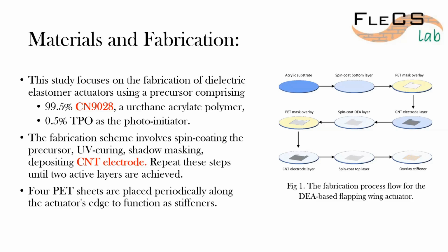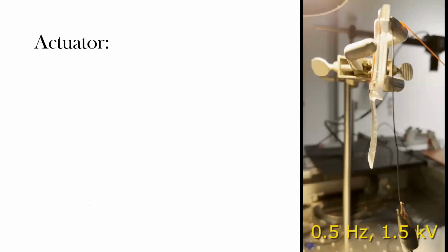And, of course, at the end, if you want a specific kind of actuation, like I said, you have to do some kind of physical constraining. In this case, we did that constraining by overlaying a stiffener, which is a PET thin film, stiffer than the elastomer itself. And we were able to get the final system done. And that's about it. It doesn't require a clean room. It requires a clean lab, but not an actual clean room.